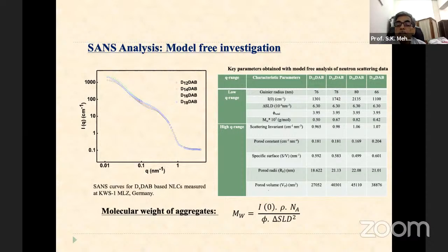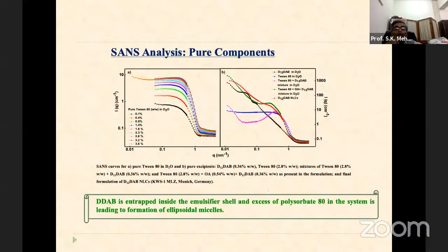So all these parameters for different types of DDAB, which can be used, and she used all this, and she used this molecular weight for aggregates MW on this, depending on I, that is intensity, density, Avogadro number, and other such parameters which have been used. So she could try for all the pure components first, and then finally she varied even the Tween 80 from 0.1% to 3.6%, and there in the second B part, all the Tween 80 in water, DDAB in D2O, Tween 80 in D2O, all combinations she tried to find out.